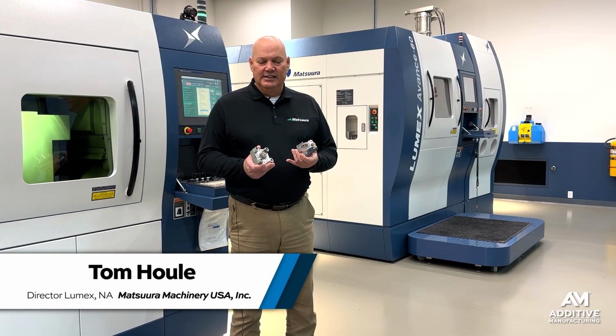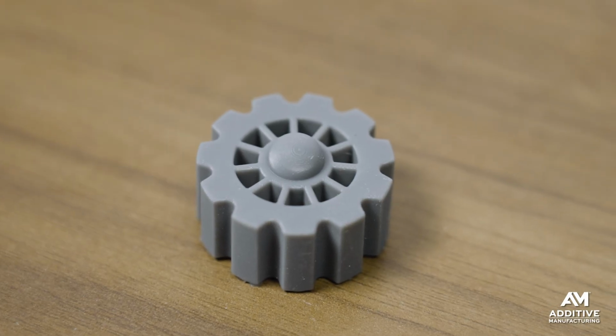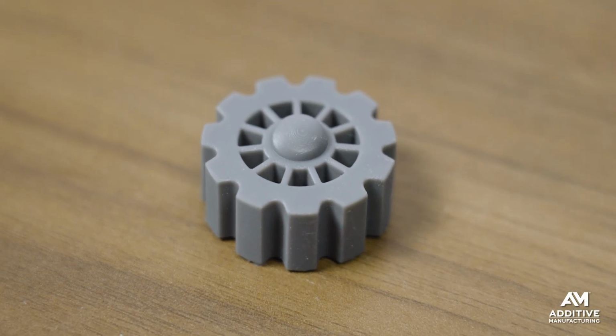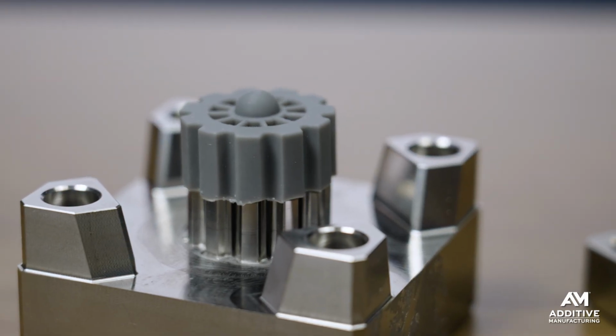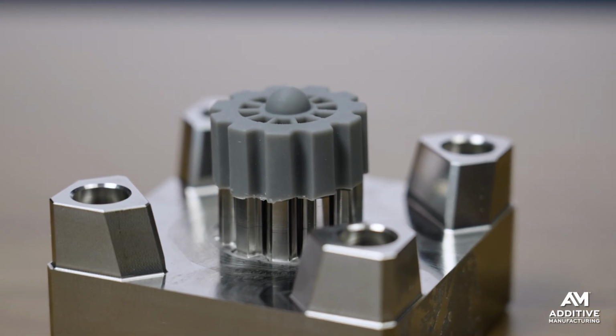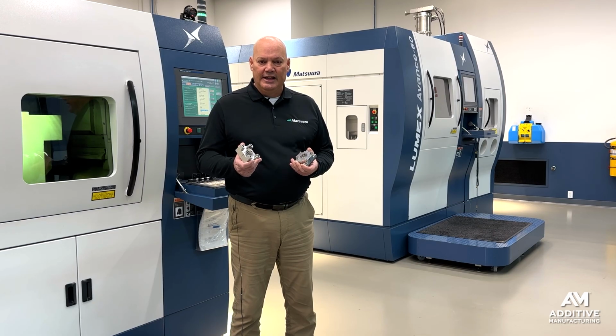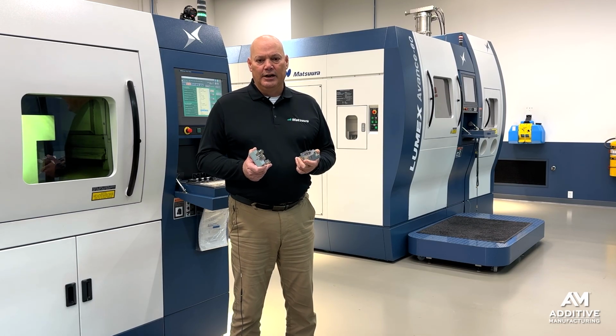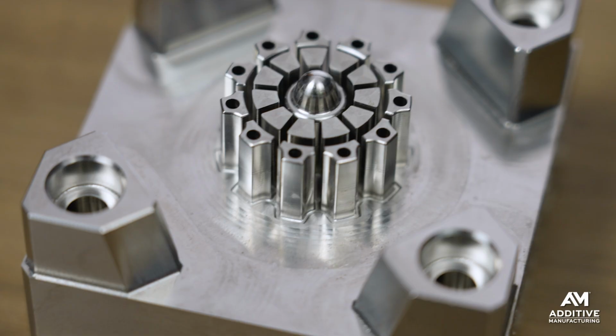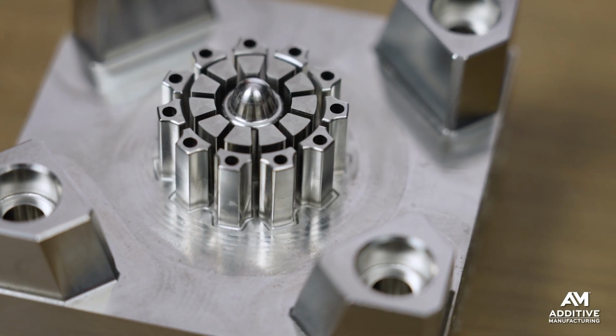Here is Tom Houle from Matsuura. It's a nylon 6.6 part. They had quoted a very aggressive cycle time to get the business. The significant problems they were having was cycle time was about 15 seconds longer than they needed it to be, and then their part quality, they were ending up with a lot of burning on these deep ribs.